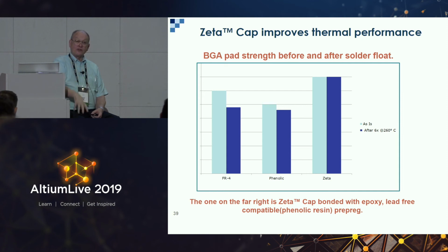I don't know if you know that, and that's because the current FR4 laminates are not very good. To get the higher temperature, they add phenolic. When they added phenolic, they made the resin brittle. And so now your BGAs can crack off the board. This happens all the time, but we mainly keep it a secret from you that we've got big reliability problems with our new FR4 materials, only because of lead-free.